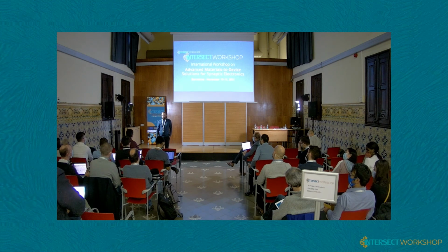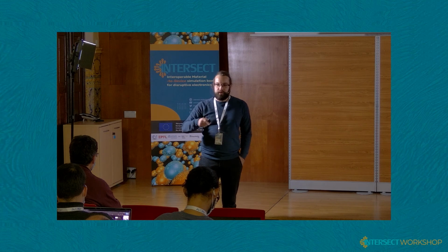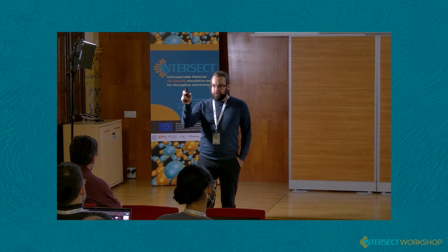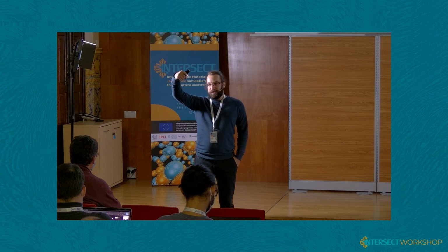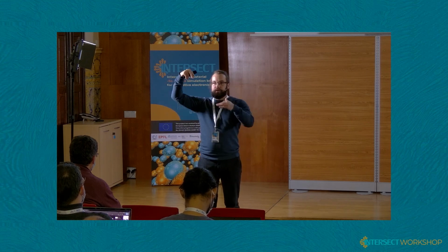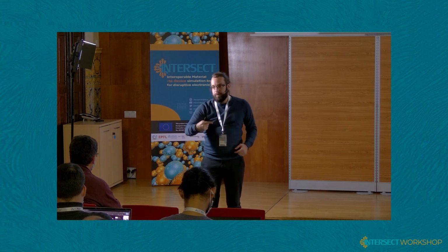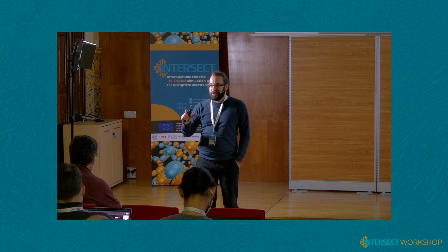Yeah, they are in the Ginestra model, though I'm not sure it's possible to see them. As you have seen already during the downsweep, the traps very close to the interface in the upper trap band were already emptied. The ones that are even further out than those on the conduction band will be out even sooner. But of course, if the wedge is formed, they will flow into the wedge and can then trap into the trap bands there. So it's kind of true, but there are a little bit more details to it.